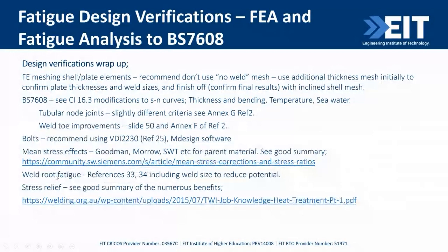For weld root fatigue, look at references 33, 34. You've got to avoid that because you'll find it with radiography and UT, ultrasonic NDT, but you won't find it visually. And then stress relieving. TWI do a lot of good knowledge links with stress relieving, the benefits and the reasons.